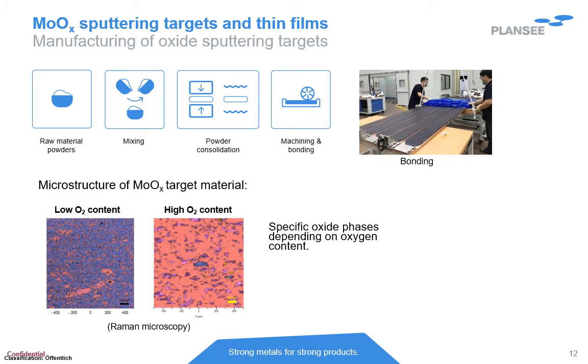The microstructure of such a molybdenum oxide target material depends on the oxygen content. Depending on the oxygen content, there are different fractional areas of oxide phases in the material, which makes it possible to tune the properties of those target materials. So for example, electrical conductivity, thermal conductivity, but also fracture strengths of those materials are strongly dependent on the oxygen content. And by using powder metallurgy, it is more or less possible to achieve the one or other property depending on the final application.